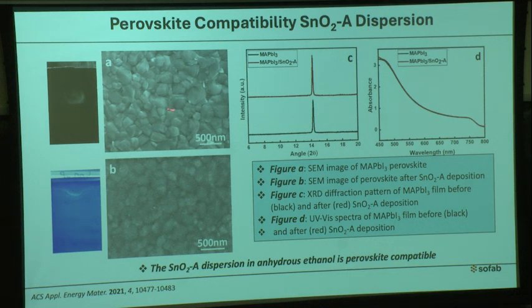If you look here, this is the scanning electron microscopic image of the fully converted perovskite, and we can see the perovskite grains. After tin oxide deposition, we can still see the perovskite grains, but they are less visible, due to the presence of another extra layer here. That's why they are less visible.